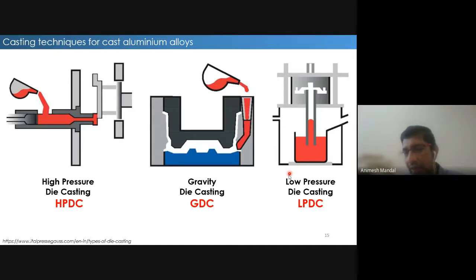The other technique which is used is low pressure die casting. As you can see, it's a counter gravity process where your liquid metal is sucked into the die. So this is a gravity process, this is by pressure, and this is a counter gravity process. You can draw the liquid metal to fill the die and control the velocity, and the die filling is very uniform, with hardly any turbulence. As a result, the castings you get are almost defect-free due to the very nature of the process.